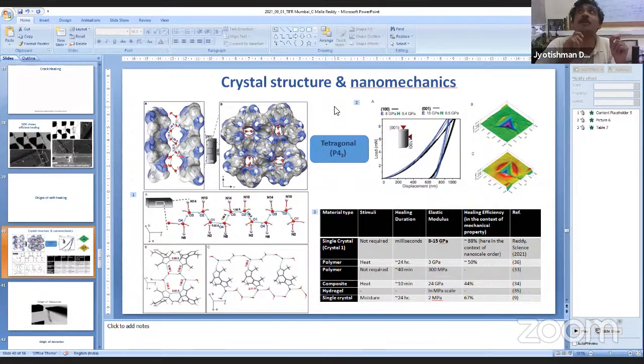If there was no signature of which atoms should be connected to which atom, and it's only purely electrostatic, I can bring two of them and join them as a perfect crystal. If I do this experiment, I don't know what the result is. But if I'm not able to do that, it means that there was a memory of how it was broken, and some charges have an atomic signature. You will have certain broken bonds which will have to reform. Only then it will be perfectly healed.